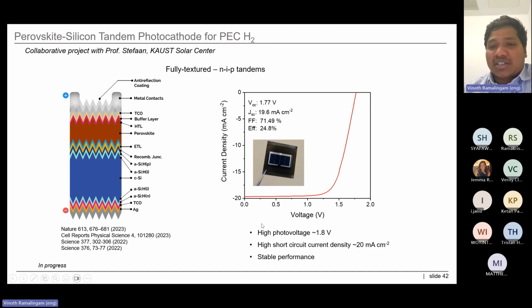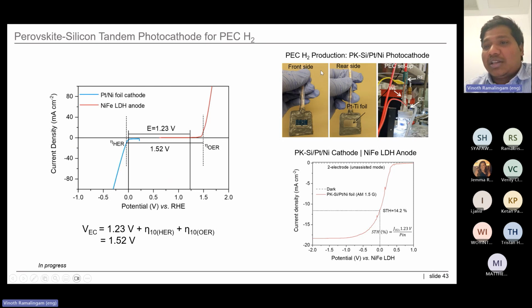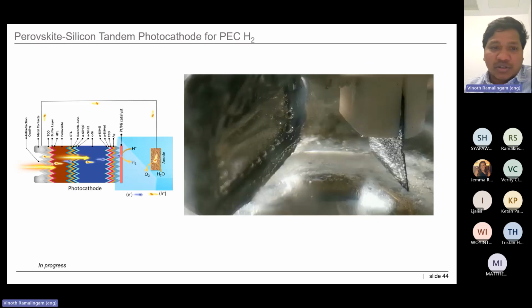So I just took their cell and fabricated it with the platinum-titanium foil as a catalyst on the rear side, and we demonstrated this device for photoelectrochemical water splitting without any bias. In that case, we were able to achieve a solar-to-hydrogen efficiency of 14.2%. So this is the device configuration. You see that I have used a horizontal illumination. On the rear side, you will get the electrons, whereas on the front side, you will get the holes. The electrons reach the platinum-nickel catalyst side, where they are involved in the hydrogen evolution reaction.